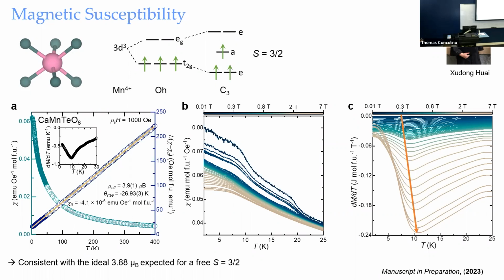However, you see it actually undergoes a magnetic phase transition, but it's very subtle. So you wouldn't see it from the chi-d by itself. So when you take the derivative here, you see there's a valley at around 10 Kelvin. And when you look at magnetic susceptibility as a function of temperature under a series of magnetic fields, you see that there are a few changes in the slope in low field, suggesting maybe there's some AFM and FM competing exchange interaction.